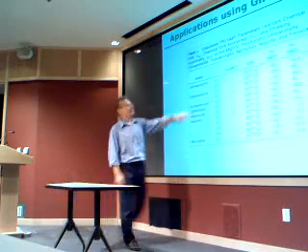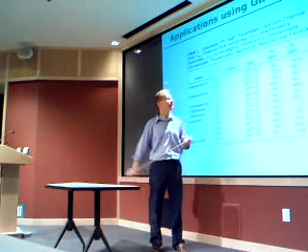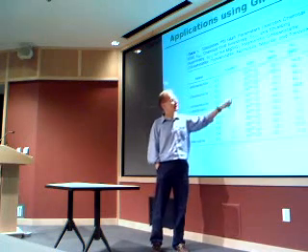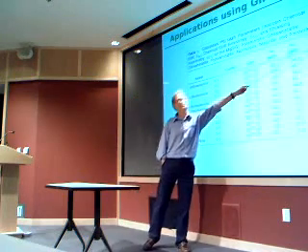Then, just to mention other kinds of materials, for instance, silicate. First they calculated some values, the isotropic, so the trace of the chemical shielding tensor. Sorry, this is the chemical shift tensor. So you take the average of the tensor, and with these numbers, they have also defined the anisotropy of the chemical shielding. With this, one can go and simulate how it would look.